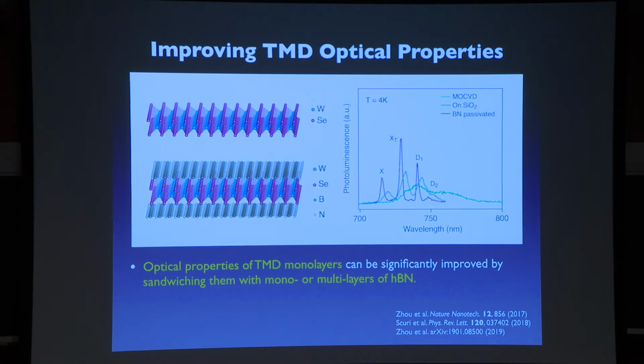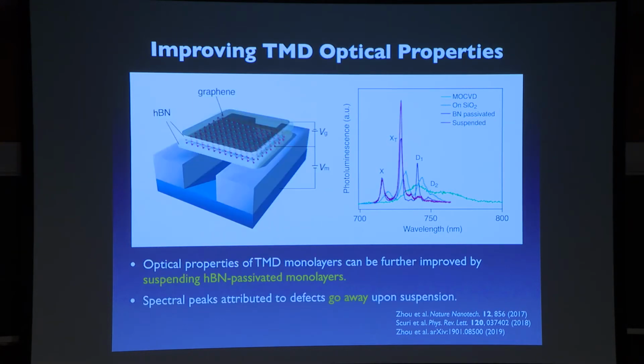The first thing that we did some time ago in 2017 was to show that when you start to passivate them using so-called hexagonal boron nitride, essentially a wider band gap material, then you can sharpen these spectral features much more. And another thing that we have shown is that if you eliminate the substrate entirely by suspending these passivated two-dimensional materials, then you can make the material properties even better.